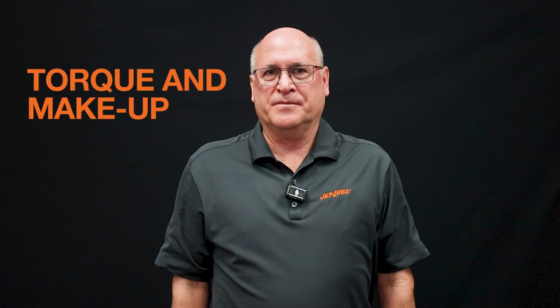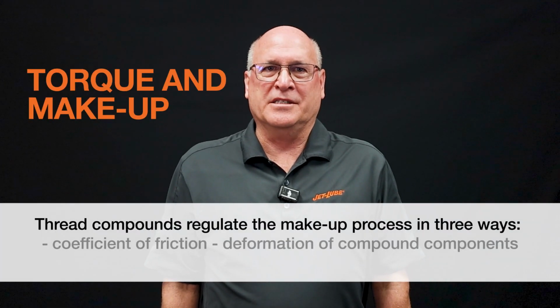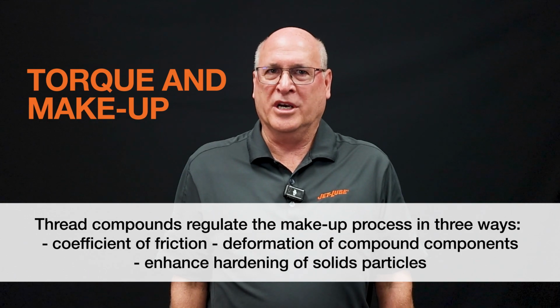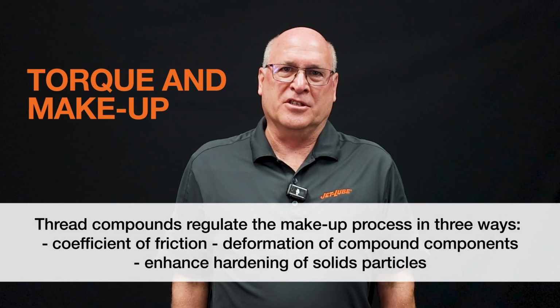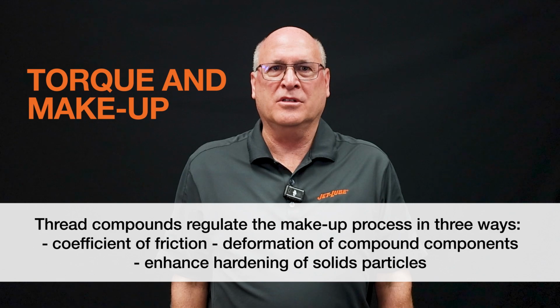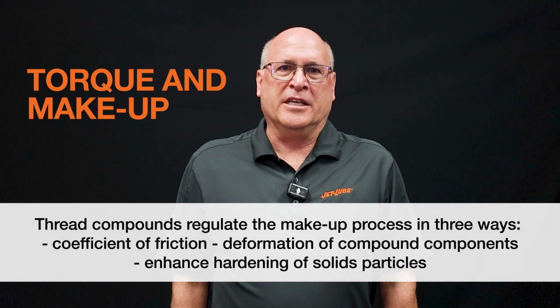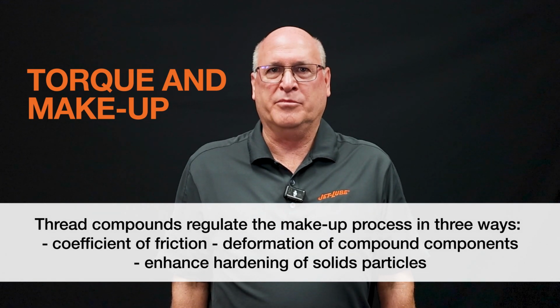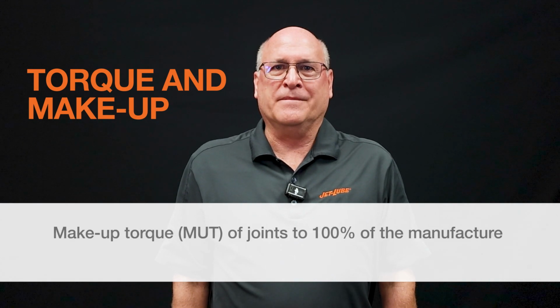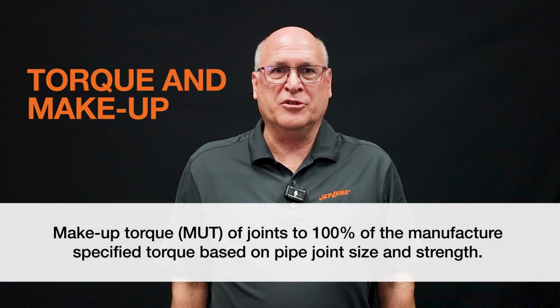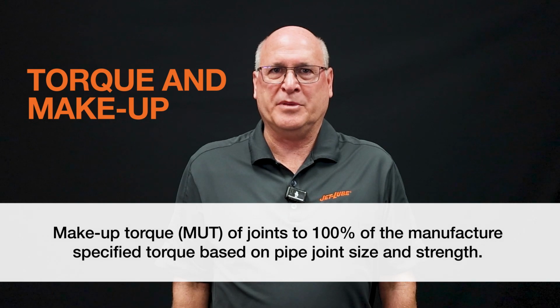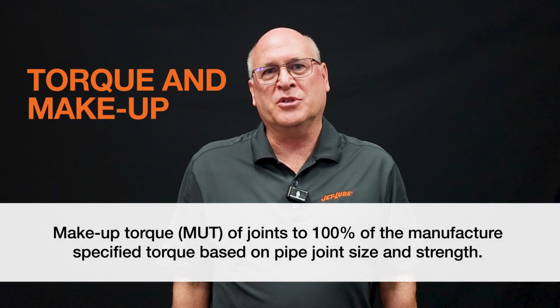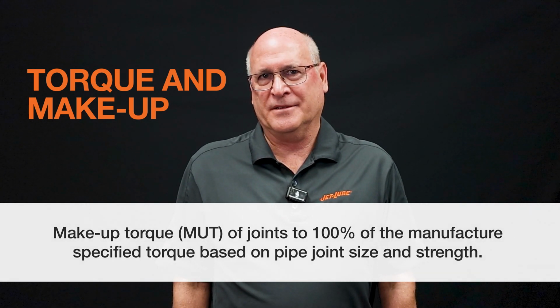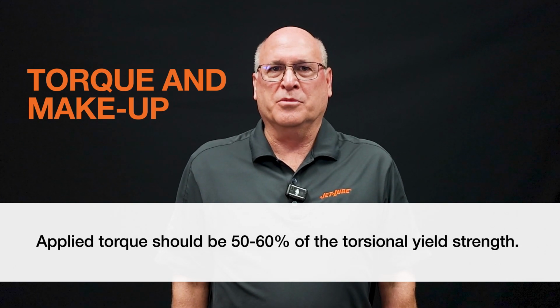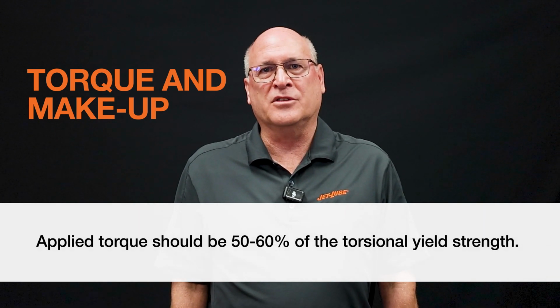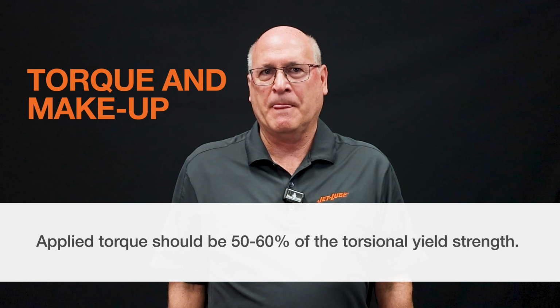Torque and makeup. Thread compounds regulate the makeup process in three ways: coefficient of friction, deformation of compound components, and enhanced hardening of solid particles. Makeup torque, MUT, of joints is 100% of the manufacturer's specified torque based on pipe joint size and strength. Applied torque should be 50 to 60% of the torsional yield strength.